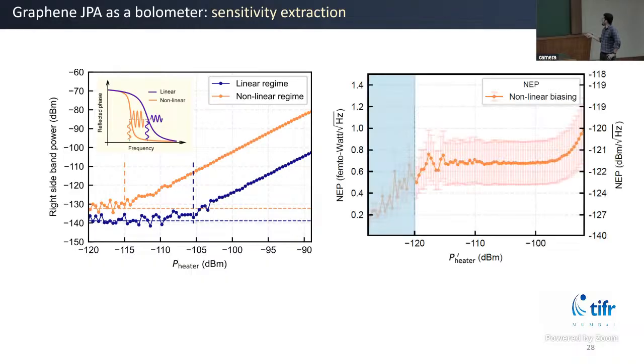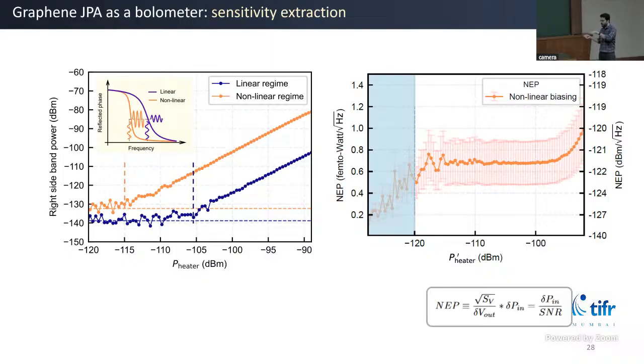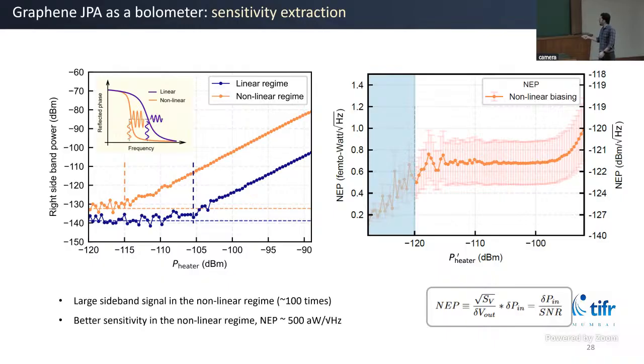Next, we try to extract the sensitivity. As I said, three key metrics: noise equivalent power. It says what is the noise floor beyond which your bolometer can sense any power. This is the definition of NEP: the minimal power you can detect when your signal to noise ratio is 1. So that basically says what is the noise floor of your bolometer. And that we found is about 500 attowatt per square root hertz. And the NEP becomes better when you go to the nonlinear region, as expected, because there the sensitivity is higher.